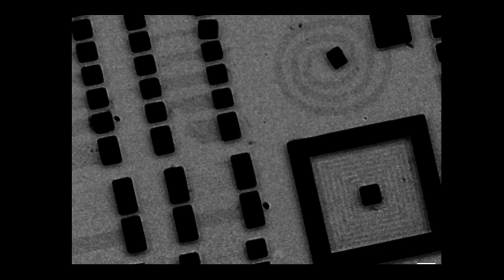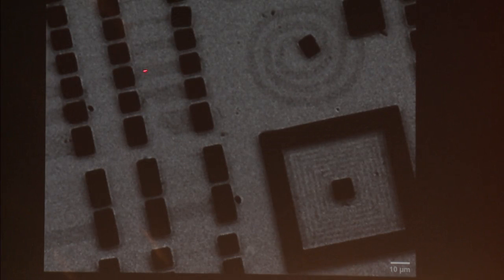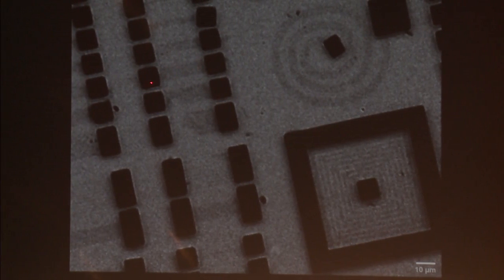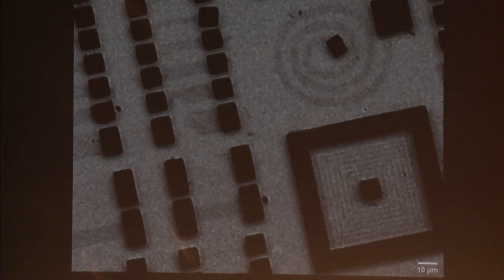Well, first off, there's a whole fabrication technology that we can use to pattern graphene, and that's illustrated by this picture here. This is an optical micrograph, and if you look carefully, you can see, for example, a swirly pattern. That swirl that you see is a monolayer of graphene seen in an optical microscope. The dark things are gold pads that are attached to it. Some of these things are little cantilevers, so there's a very faint atomic layer sheet there with 2 contacts on it, and we can go with probes and pick up on these contacts and play with the individual sheets. And for example, to measure the bending stiffness, we'll just pick up one of these little objects here, and I'll show you what that looks like.